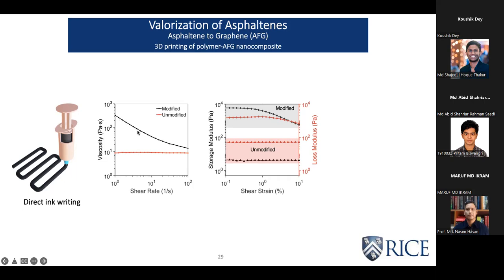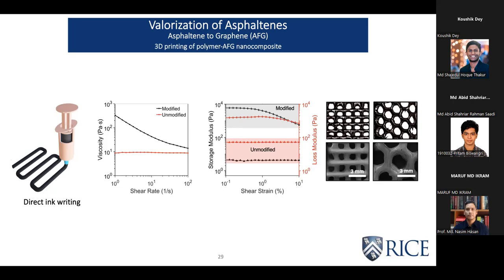Basically, the viscosity needs to show a shear thinning behavior, and there also needs to be a relation between the storage modulus and the loss modulus. At low strain rates, the storage modulus needs to be higher than the loss modulus, and at higher strain rates, the opposite needs to happen, so that during extrusion the material can flow, and after extrusion it can retain its shape. So we obtained this type of rheological response after we added the rheology modifier and optimized all of the contents, and we were able to 3D print the architected structures, which look like this.